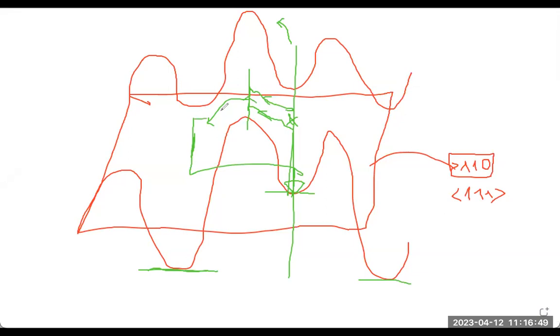And this dislocation evolves, and they move to the lower energy state. These parts are called kinks. Let me write kink. Basically, the movement of screw dislocation is thermally activated and with kink formations.